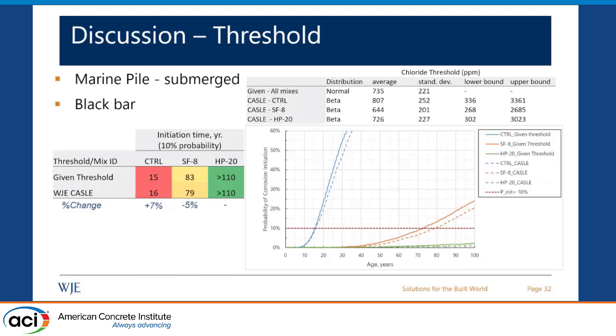So here, comparing the two, when we're looking at the control mix, we estimated 1 year greater than the predicted service life if we're using the given threshold, but considering the short predicted service life, this is actually a 7% change. With the silica fume mix, we are predicting 5% less in terms of predicted service life compared to the given threshold. For the natural pozzolan, we're not seeing much change, especially that we're looking at 110 years as our analysis period here.